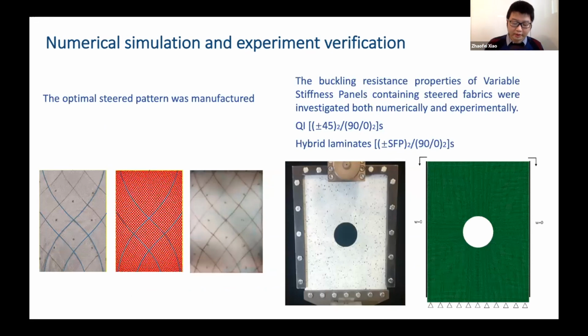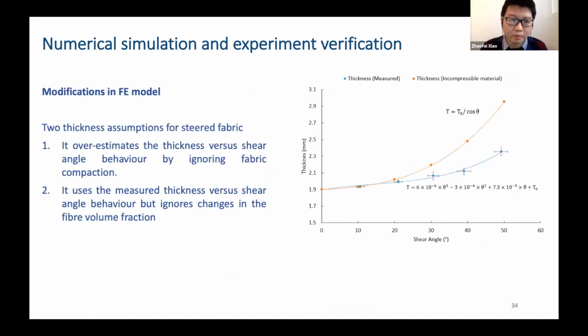Then, after we determine the optimum steered pattern, we manufactured one and conducted the buckling test and compared the results against the numerical simulation. And I should mention that in the new simulation, I did some modification. Firstly, we use two thickness assumption methods. The first one is what we used before. We assume the fabric is an incompressible material, but it overestimates the thickness of the fabric because we ignore the fabric compaction.